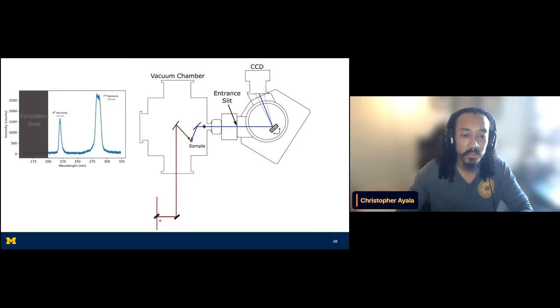Once we send the same intense light into this vacuum chamber and focus it onto the sample, we now have a grating spectrometer with a very, very sensitive camera. This sensitive camera should be able to pick up harmonics that are generated within this forbidden zone that I had mentioned earlier, because now that the sample is in this vacuum chamber and we pump it down, we should be able to generate harmonics that are into the vacuum ultraviolet range.